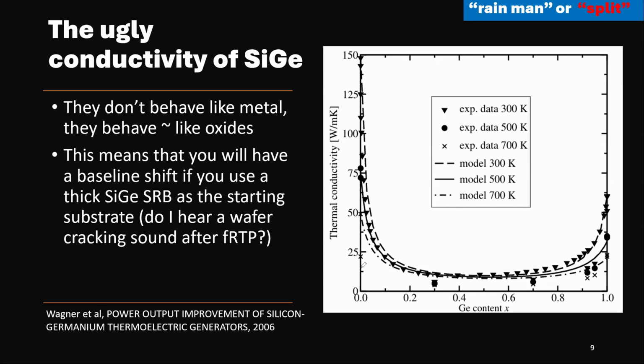If you look at the thermal conductivity curve of any alloy, it should be proportional, right? This is germanium 0, it means pure silicon here. This is pure silicon. And then germanium equal to 1 is pure germanium, right? It's pure germanium. In theory, intuitively, you would think it doesn't matter who's good and bad. It should be linear like this, right? Metal, you mix two metals together. One is a little bit better than the other. This is 150 watt per meter Kelvin, and the other one is like 60 to 80. So it's like 2.5x off. But it still has to behave like this, right? Linear. That's our intuition. If you mix copper and gold, copper and aluminum, that's what you expect.